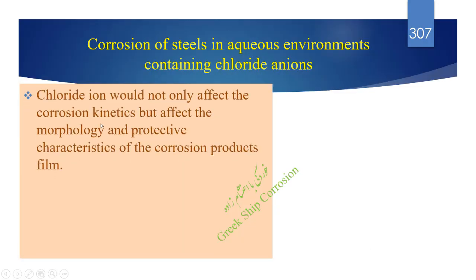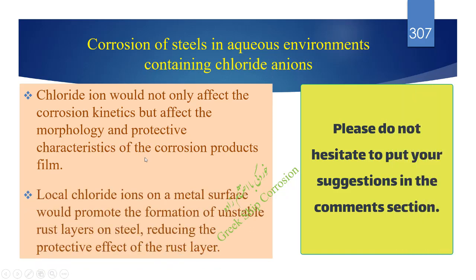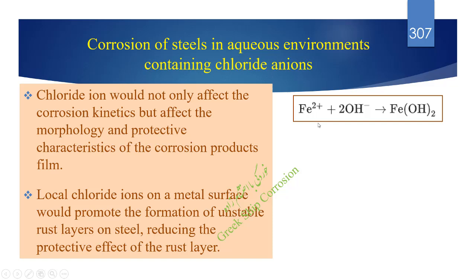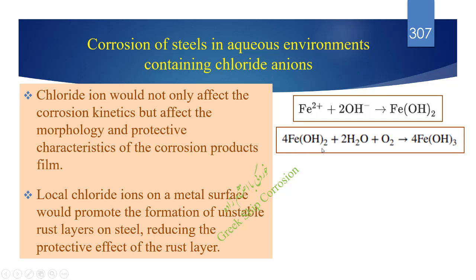Chloride ion would not only affect the corrosion kinetics but also the morphology and protective characteristics of the corrosion product film. Local chloride ions on a metal surface would promote the formation of an unstable rust layer on steel, reducing the protective effect of the rust layer. Fe2+ + 2OH- yields Fe(OH)2. 4Fe(OH)2 + 2H2O + O2 yields 4Fe(OH)3.